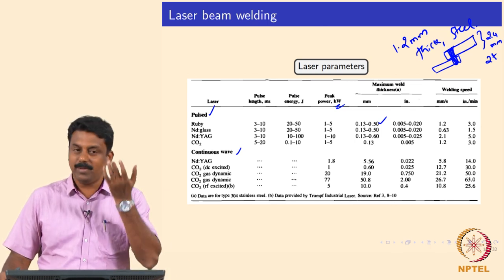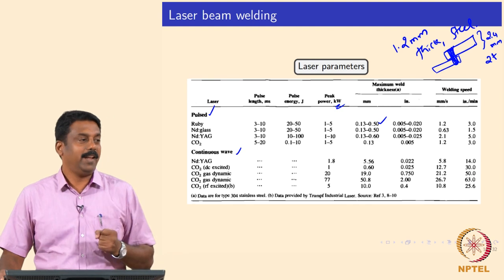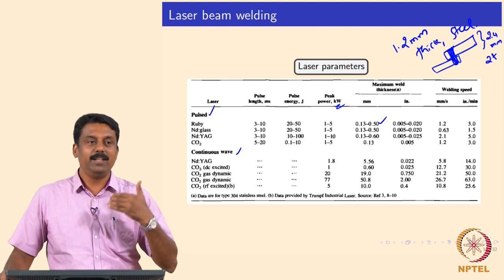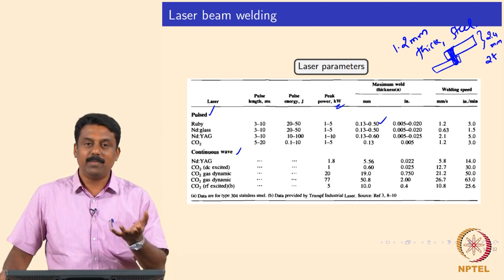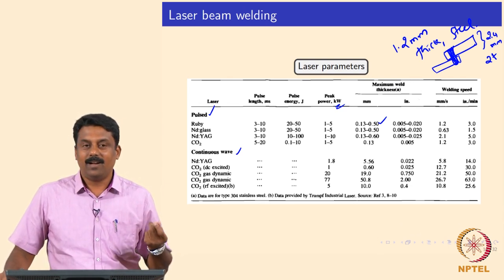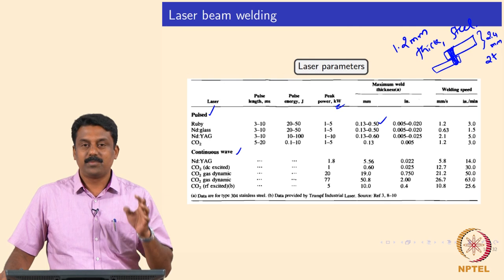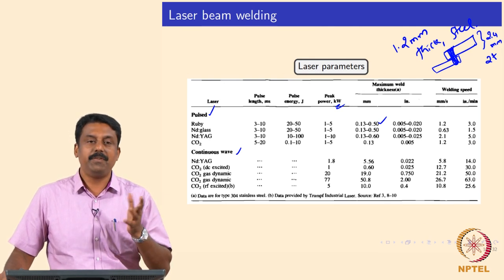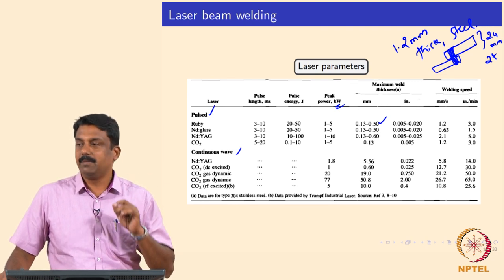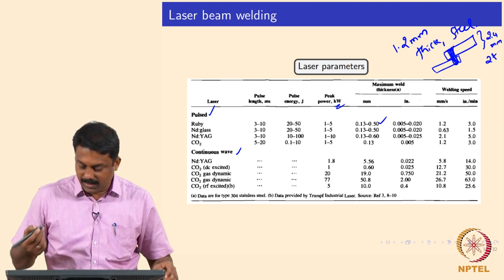Aluminium does not absorb light well - that is the reason when you heat up aluminium it always remains white because everything is reflected. Whereas if you heat up iron, you see the change in colour, meaning all other colours are absorbed and only the orange colour is emitted. So there is some absorption. When you use laser welding of aluminium alloys, the absorption is very minimal - only 10 percent - so efficiency of laser welding of aluminium alloys is extremely poor because of the poor absorption.